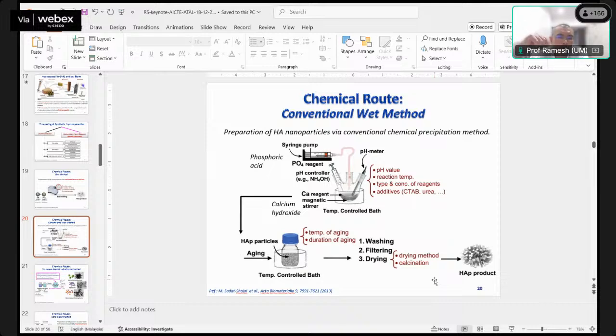And then we use a precipitation method where we have the calcium hydroxide placed in the beaker. It is stirred by a magnetic stirrer, and we titrate the phosphoric acid into the beaker that contains the calcium hydroxide, and we control the whole process. We monitor the pH, we monitor temperature, and so on, and based on that, we are able to obtain hydroxyapatite. Thereafter, we clean the byproduct from the reaction, and after washing, we filter it, and then we dry it and we obtain the hydroxyapatite powder.